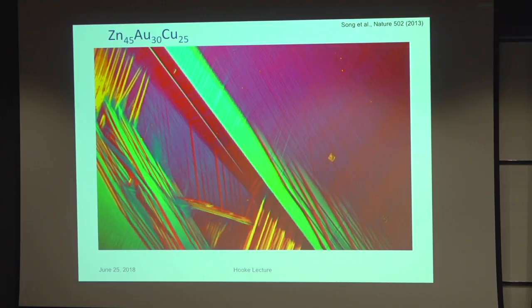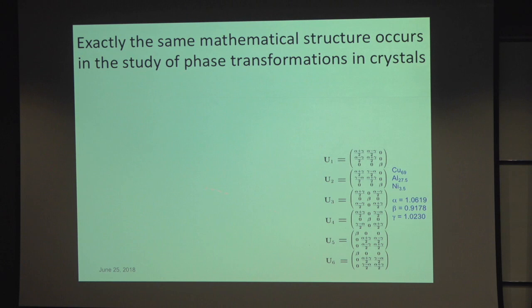As John was saying, these phase transformations are incredibly interesting. And I'm going to show you one in which, just like origami, you get to play with those six matrices by changing the so-called lattice parameters, alpha, beta, gamma. You get to change the distortions, so maybe you could have very special distortions in which the two phases fit together in many, many ways. You get many, many origamis. In fact, that is exactly the truth: if you tune alpha, beta, and gamma to some special values, then you get many origamis possible with these crystal structures.